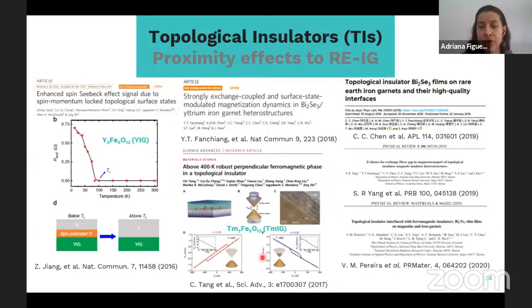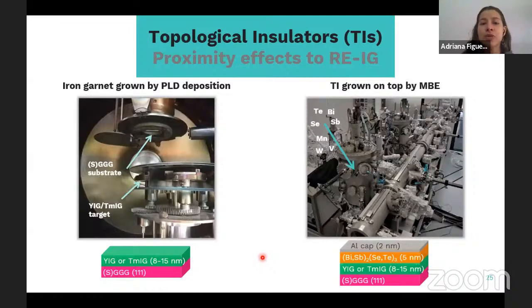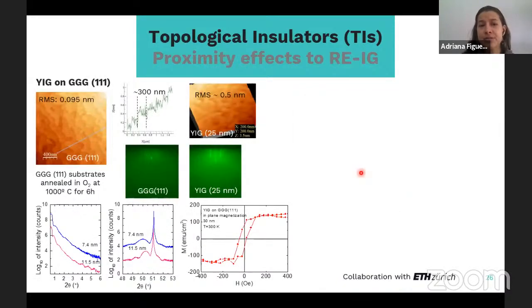So we grew our samples as well. In this case, we grew the iron garnet by pulsed laser deposition on GGG substrates, on gadolinium gallium garnet substrates, and then we took them to our MBE to grow the topological insulators on top, and then we grew our films. And then what we see, just a brief characterization of the magnetic layer. Our YIG samples are of very good quality, as revealed by characterization like AFM or XRD.